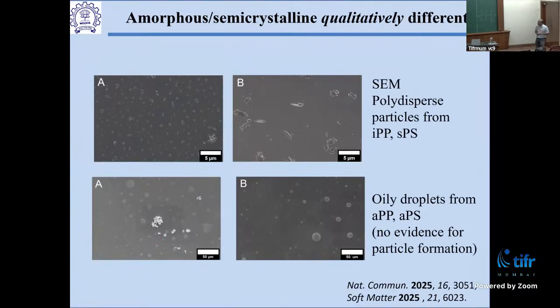Right. So now we went back and looked at the stuff in water. So I have particles. What do those particles look like? Why do the amorphous polymers not scatter? And so this is SEM data. This is for isotactic polypropylene. This is for syndiotactic polystyrene. So two different chemistries. Both of these are crystalline. And what you see is you can very clearly identify that there are particles in there, right?